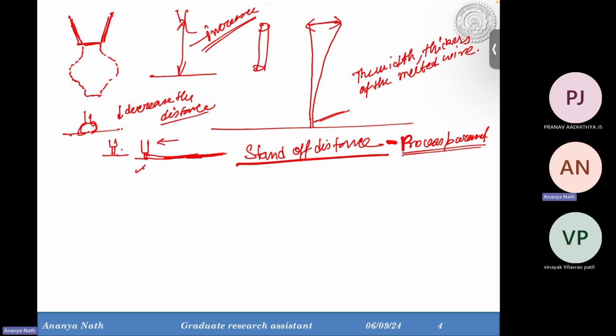because all of a sudden the wire was a solidified thing and now it is getting melted and coming out of it. Because of the viscosity, it will look like this and then it will deposit like this. There will be an expansion of the liquid, because it was inside the wire and suddenly it is coming into the ambient pressure. So obviously there will be an expansion of the liquid or melted wire. Because of that, you may have some distortion in your part if your stand off distance is really very low.